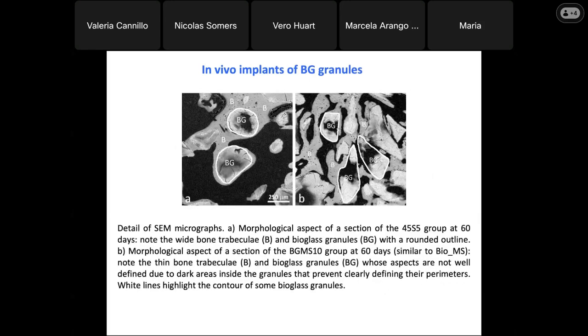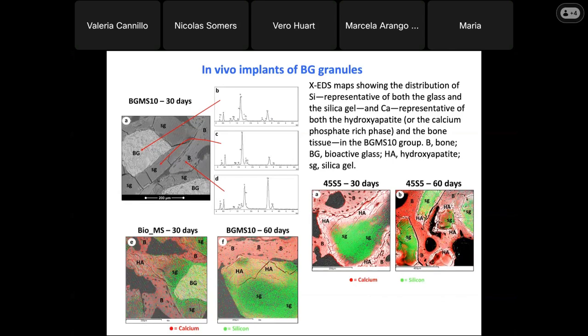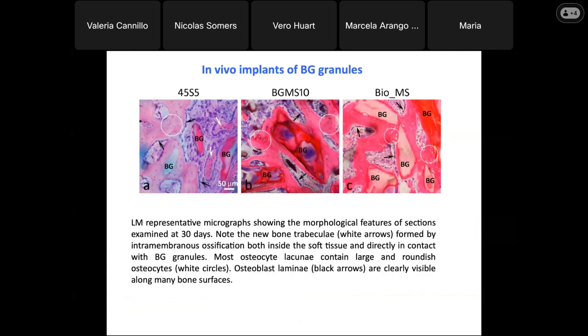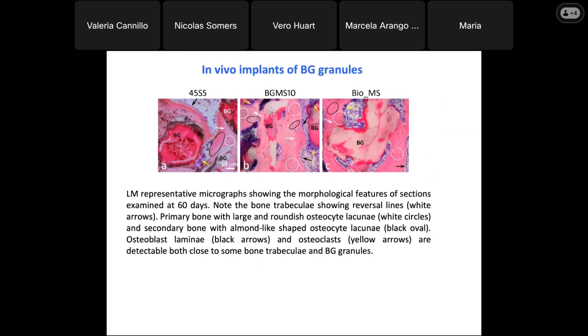And here, for example, you have some zoom still evidencing after 30 and 60 days some residual bioactive glass granules. But we also had EDS maps for showing the distribution of silicon, which is representative of both glass and silica gel, and of calcium, which is representative of hydroxyapatite or bone tissue. And more interestingly, here you have histologies. So these are light microscopy images of a section of a bone of rabbits after 30 days, and you see new bone trabeculae. And here you have the same kind of analysis after 60 days.